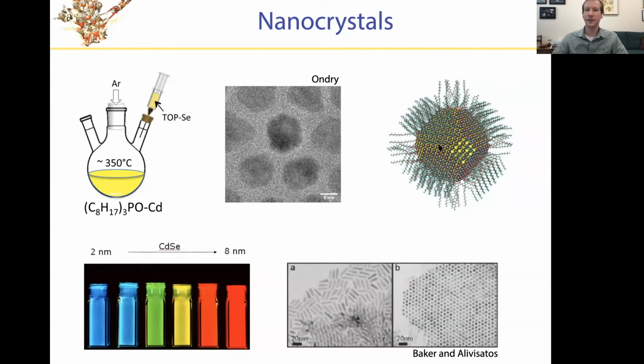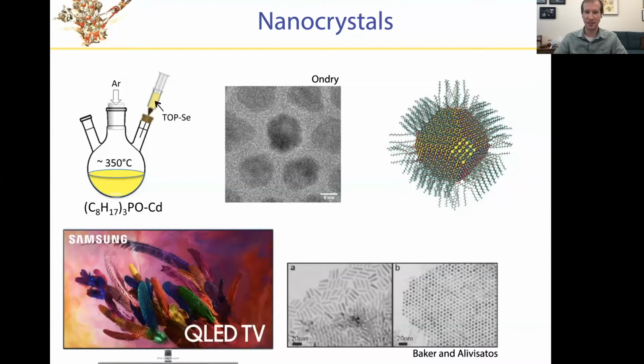These crystals, while they share the crystalline lattice structure of their macroscopic counterparts, have distinct properties. Perhaps the most famous one is that the color of cadmium sulfide, the color of its photoluminescence, changes distinctly as the size of these nanocrystals changes. This is an iconic picture now of nanoscience, illustrating how the size of these particles from 2 nanometers to 8, this is a closely related material, cadmium selenide, changes dramatically the color of this really brilliant photoluminescence. This is one area of nanoscience that has already really come into the marketplace, and there are now TVs that are based on precisely that photoluminescence of quantum dots, of nanocrystals. And once something's in your TV, it's here to stay.